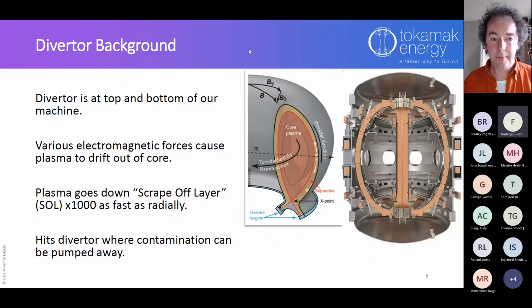So I thought I'd explain the bit I work on. Here's another picture of the tokamak, and you've got your core plasma in the middle, going round and round in a donut shape. Now, it's been confined by the magnetic fields, but inevitably some of those ions will emerge from the core plasma and hit the outer wall of the vacuum chamber. As they are very, very hot, that will cause sputtering and melting, possibly. And as soon as that happens, you've got metal particles, which are very high mass, flying around, and they disrupt this confinement of the core plasma. They radiate away energy and cause all sorts of trouble.